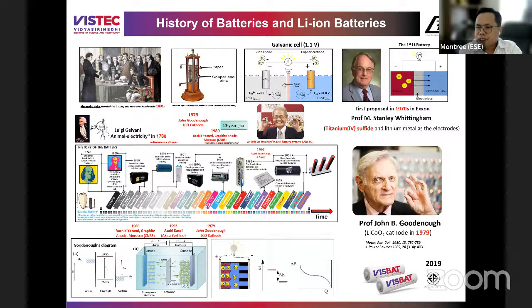Then Professor John B. Goodenough, at that time he worked as the head of the inorganic chemistry department. He invented lithium cobalt oxide. He put lithium inside the layered material, cobalt oxide. It's more stable than sulfide compound. And in his material, he had lithium there. So based on this compound, it's not necessary to use lithium metal at the anode anymore, because we start with lithium cobalt oxide at the cathode, right?